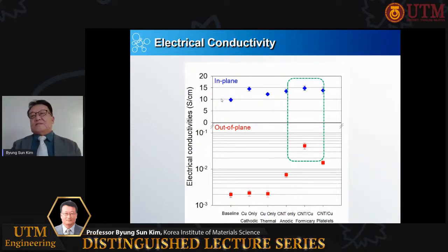The graph represents the electrical conductivities for various nanocomposites. The nanocomposites are by copper only by cathodic process, copper only by thermal process, CNT only by anodic process, CNT copper formicary, and CNT copper platelets. The in-plane electrical conductivities for all nanocomposites appear to have fairly similar values. However, the out-of-plane electrical conductivity is the highest with CNT copper formicary nanocomposite, and the CNT copper platelets nanocomposites show almost as good values.